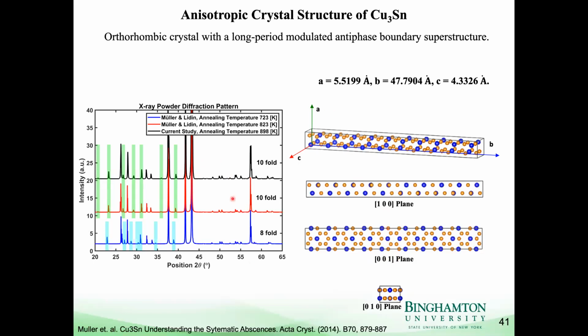In the literature, both tenfold and eightfold superstructures have been observed, but not together. So if you make a sample, it's either all tenfold or all eightfold that's been observed in the literature. From the XRD, we could see that we have this tenfold superlattice that is formed. Based on certain peaks here, the ones highlighted in green are peaks that are unique to the eightfold repeating structure. So we can see that we have this eightfold structure that's emerged.